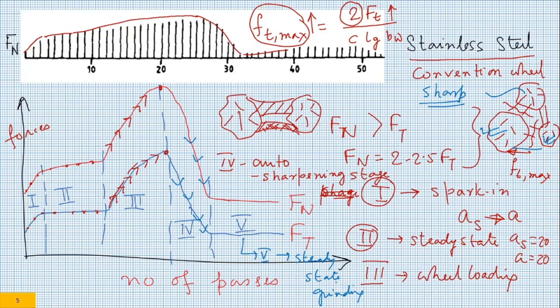How have they been exposed? They have been exposed because the external grits have been removed by the auto sharpening process. Why have the external grits been removed? External grits have been removed for the simple reason that the force coming onto a particular grit was too much, and for that reason they got removed. How were they removed? They were removed by bond fracture.